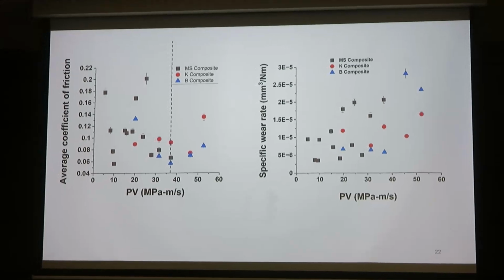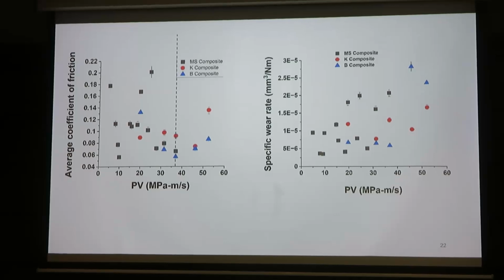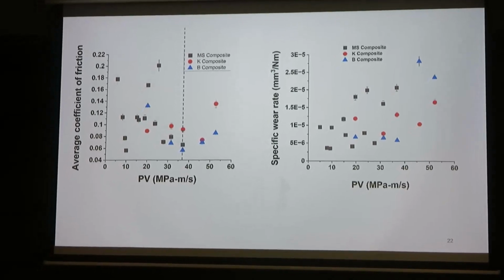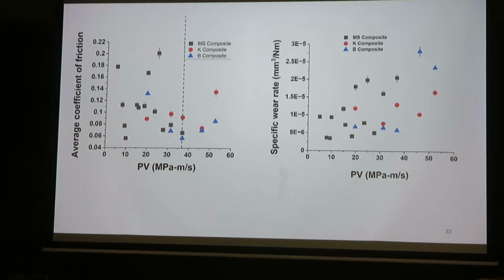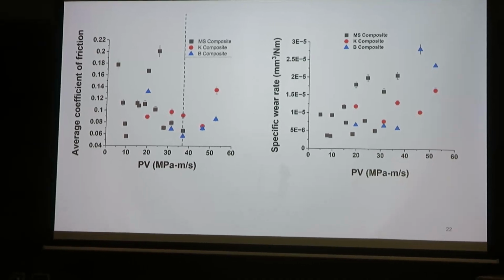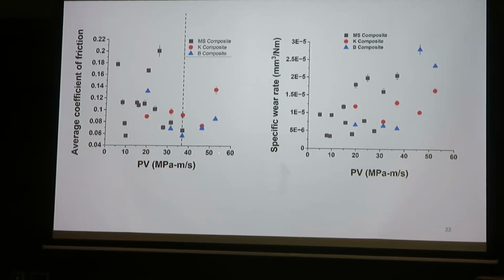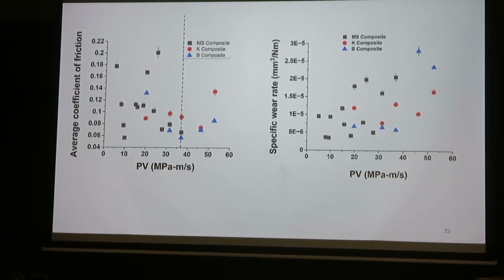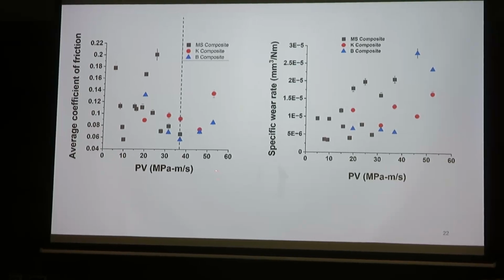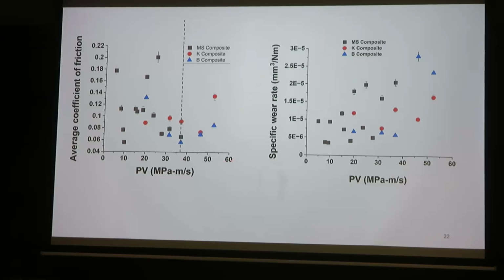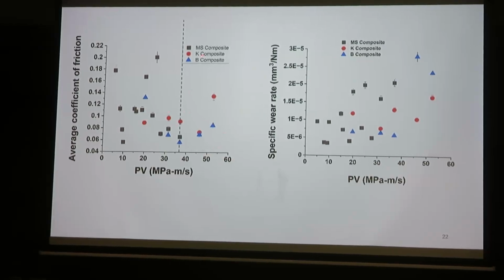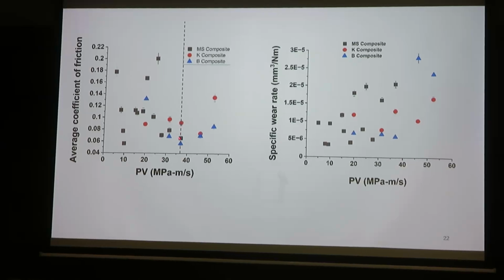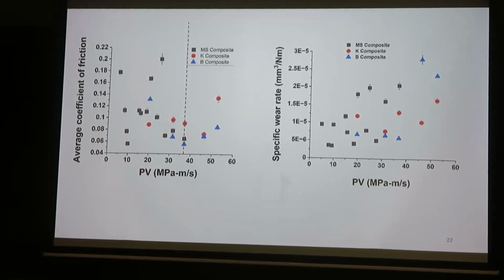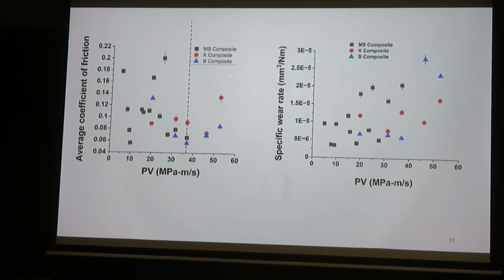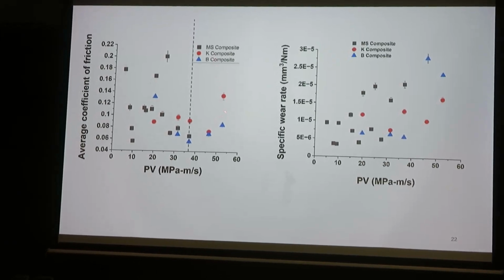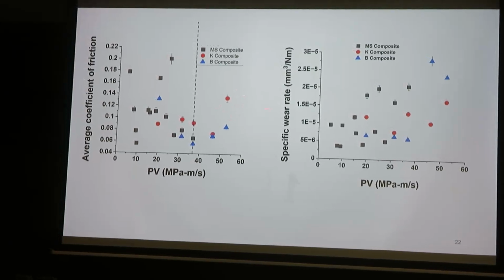Because PV is a very good parameter to understand whether your material is actually capable of handling very high stress and high sliding speed. So here the PV comes out to be quite high, up to 50. Actually, in the literature you cannot find polymer composites which have been tested for up to 50. And some of the composites, like the MS composite, which is the base composite, actually failed at around 37, so it could not go further. But other composites, with Kevlar and with basalt, actually survive even at very high PV factor.